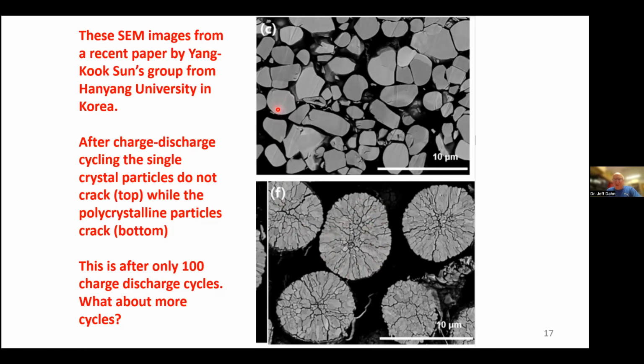But if you use single crystal materials, which are not made up of a whole aggregation of small particles fused together, but each particle is just one single crystal where the crystal axes are spanned throughout the whole particle without interruption, then this thing will just expand and contract as a whole, and there's no ability for microcracking to occur. So this is after 100 charge discharge cycles, and there's no microcracks in any of these materials at all. So what happens after more cycles?